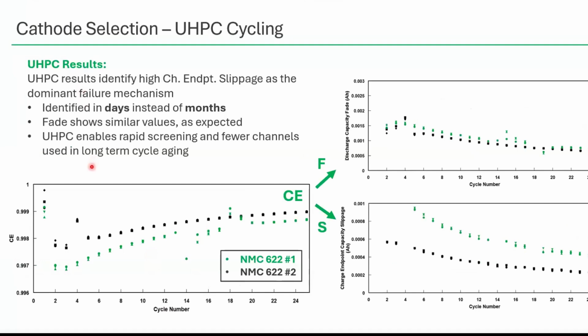When we dive in, again very much the same as the last experiment, we see that very early on, the NMC 622 number 2 has a much higher Coulombic efficiency than number 1. And this alone isn't enough to tell us why the cell failed. But if we break that up into the fade and the slippage base terms, we can see the fade is almost exactly the same.